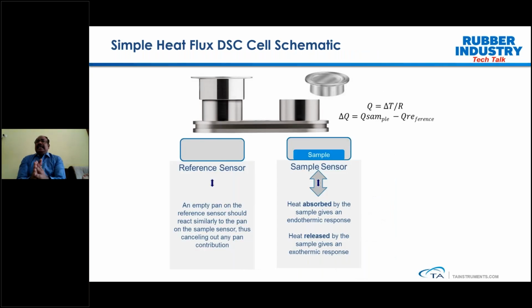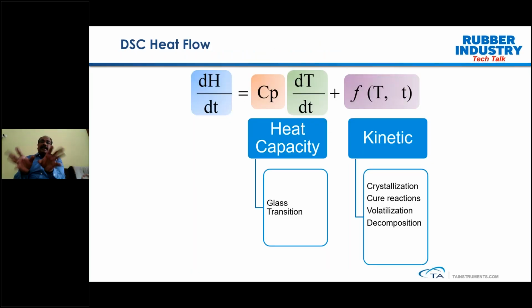If you look at heat flux DSC, there are two concepts. One is heat flux DSC, the other is power compensation DSC. Heat flux DSC, as offered by TA, has many better advantages compared to power compensation DSC. In a heat flux DSC, you have a single furnace. In fact, you have a reference sensor and a sample sensor. You keep a few milligrams of sample in a crimped pan on the sample sensor, and then we see how the temperature of the sample changes with respect to temperature.